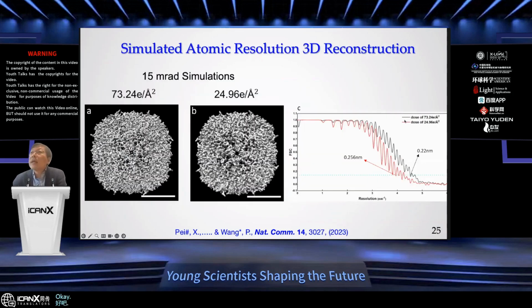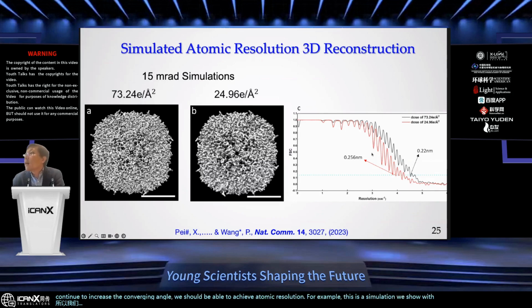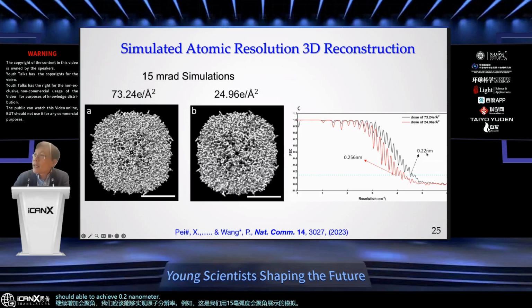Okay, so if we continue to increase the converging angle, we should be able to achieve atomic resolution. For example, this is a simulation we show with 15 milliradian converging angle, where we should be able to achieve 0.2 nanometer resolution in three-dimensional reconstruction.